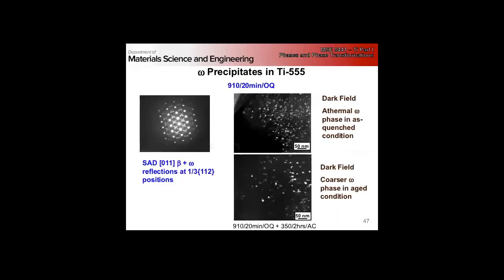Right, and this just shows how fine these omega phases are, right? This is a 50 nanometer bar, right? So these are 2 to 3 nanometer size omega regions, right? And if we age, we coarsen to say 5 to 10.